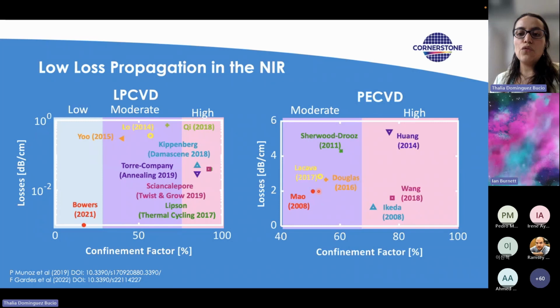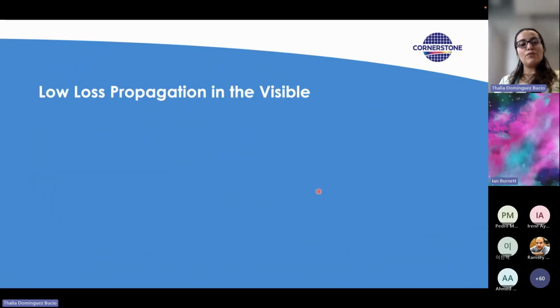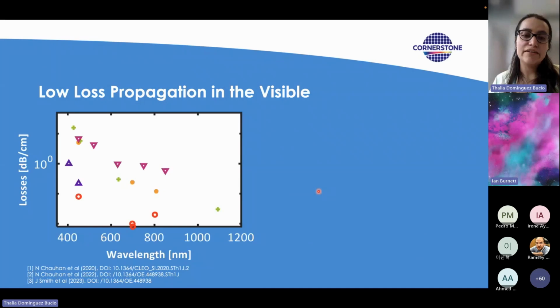Now, if we move to the visible part of the spectrum, we will see that we can also achieve low loss waveguides. So in this case, if we cover the whole wavelength range from 400 or 450 nanometers to, let's say, 900 or 1000 nanometers, we will see that we can achieve losses of less than 5 dB per centimeter. Some of the first demonstrations were done using layers of 100 nanometers to cover all these wavelengths, and with these layers, it was possible to achieve losses below 6 dB per centimeter at the lowest part of the spectrum, and then reduce the losses all the way to less than 1 dB per centimeter in the longer part of the spectrum.